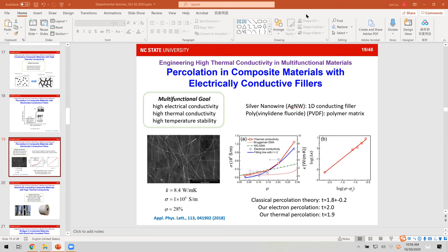Yeah, thank you for the comment. I think the reason why we started this study of nanowires in the polymer is trying to see whether thermal percolation behavior is the same as electrical percolation. It turns out there are probably slight differences. Electrical percolation will happen a little bit earlier. Yeah, I want to dig into it. And once you add enough fillers, there will always form a network. So that's why electrical percolation is always observed, or very often observed, in composite materials.